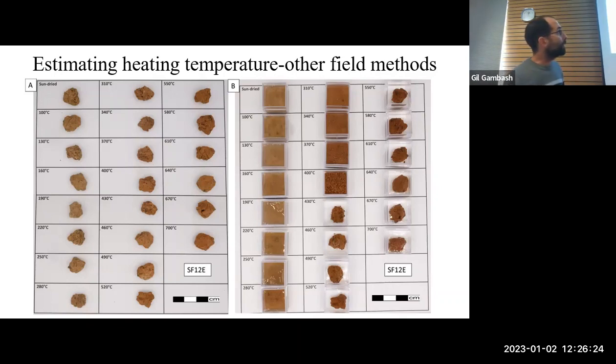Another thing that we did is we put them in water and looked at the disintegration. So these, you see, just by putting them in water, they disintegrated, those heated up to 400 degrees Celsius, and those that were heated to more than 400 degrees Celsius didn't disintegrate. But again, this is only useful from a certain temperature and up. What do you do to understand the lower temperatures?